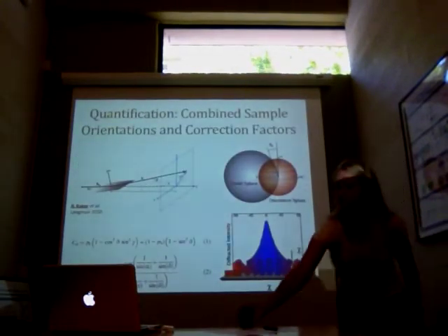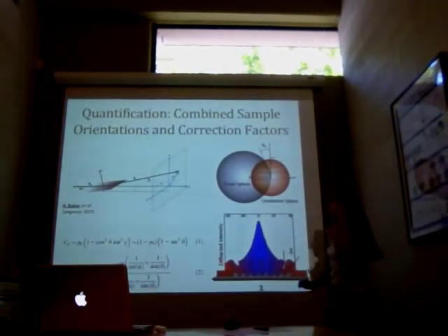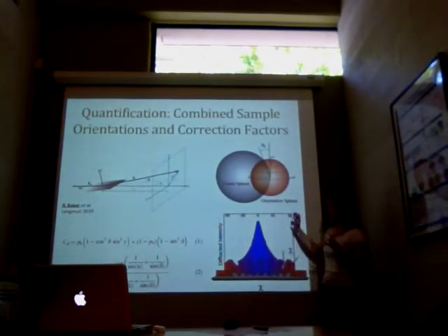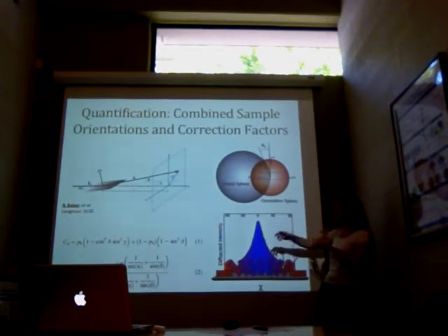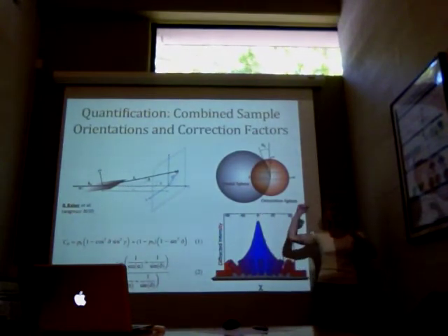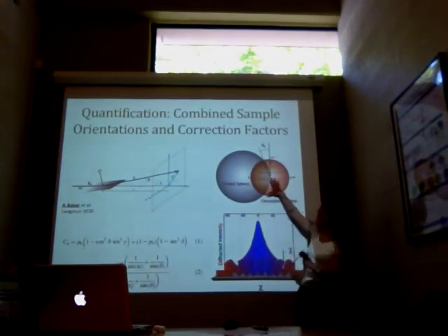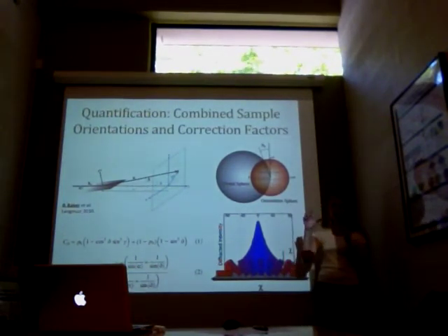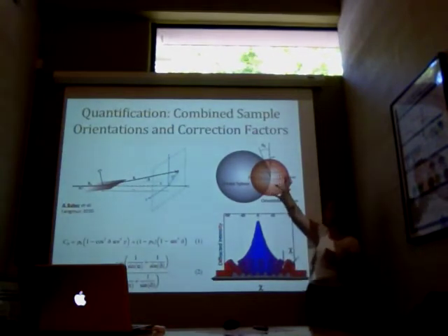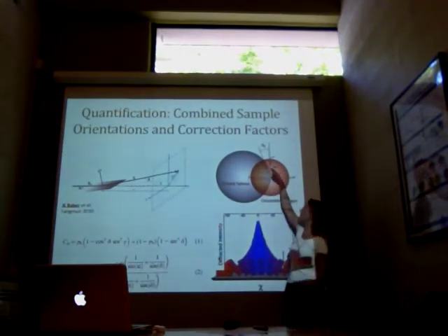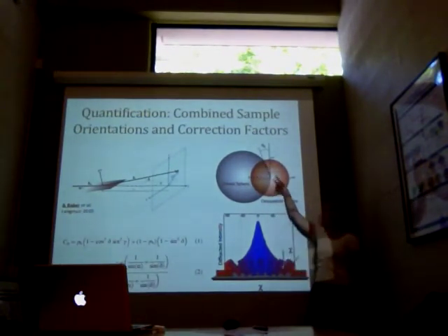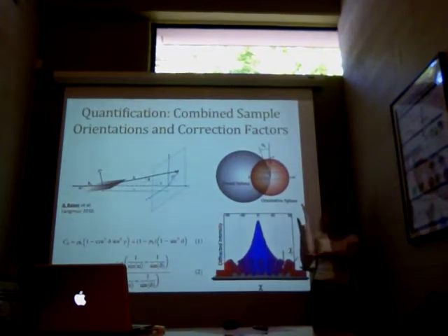Okay. So this requires a little bit of background in X-ray diffraction, but if you're looking at reciprocal space, you have something called an Ewald sphere, and it will interact with your orientation sphere, how your rods are aligned. The diameter of this is inversely proportional to the crystallographic spacing that you're measuring. And so if you only have it in one orientation, you can look at nanorods that are anywhere between horizontal and this angle. But you can't see the nanorods that are standing perpendicular.